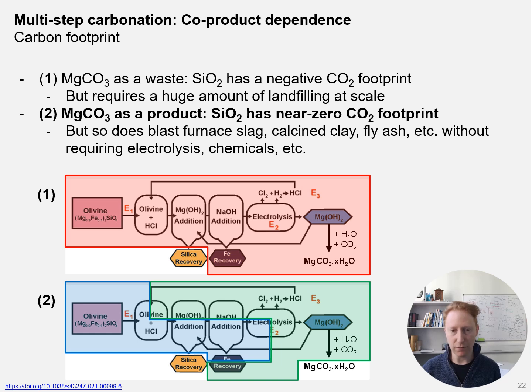But for those conventional supplementary cementitious materials, we don't require the complex processing that is required here to generate this silica supplementary cementitious material. So it doesn't make sense to think of this multi-step CO₂ mineralization process as one that outputs a carbon negative supplementary cementitious material. This should rather be thought of as an emerging concrete brick or block production process based on magnesium carbonates.